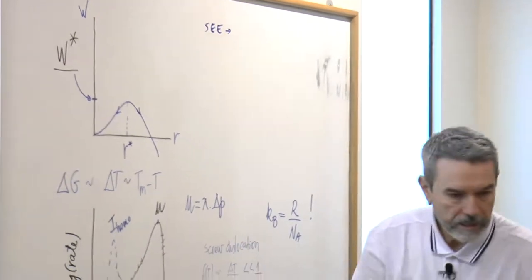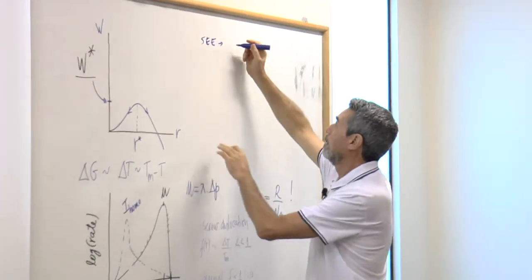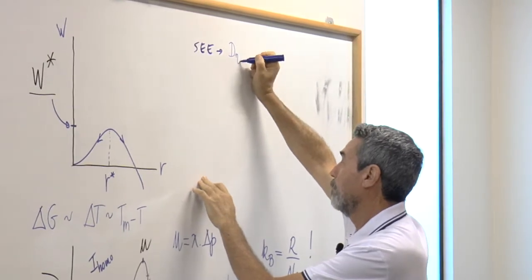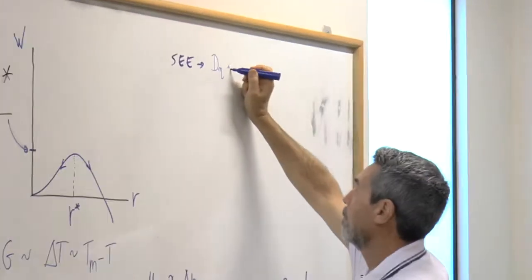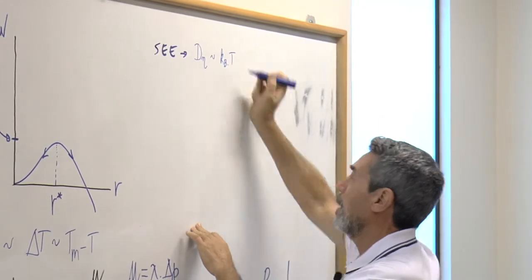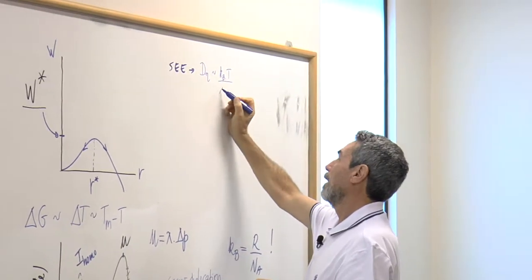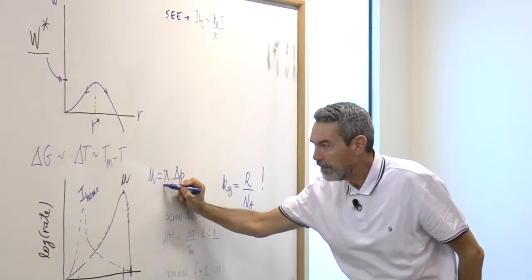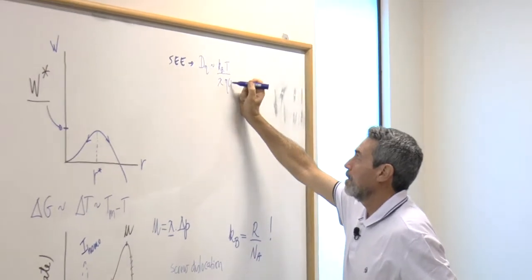The Stokes-Einstein-Eyring equation indicates that the coefficient of diffusion controlling viscosity is proportional to the Boltzmann constant times the temperature divided by lambda, our jump distance, this lambda here, and the viscosity.